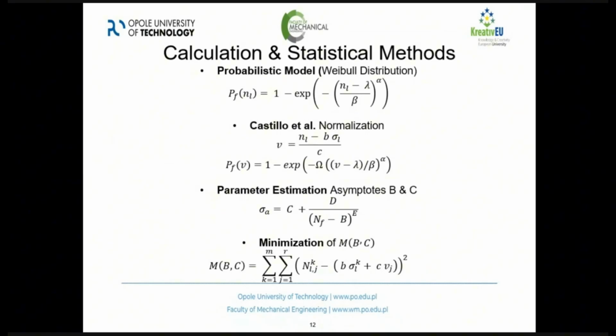Normalization method to normalize the fatigue lives to a stress-independent standard variable that can be later scaled, but it's not related to the model. It doesn't take into account the size, but we do have a scaling factor here, the omega. This is the Weibull distribution, but with normalized variable, also with the omega that basically scales the model to a different volume of specimen. Then we could get the asymptote for the model, and just to show it on the slide, there's a minimization function that will be talked about a little bit later.